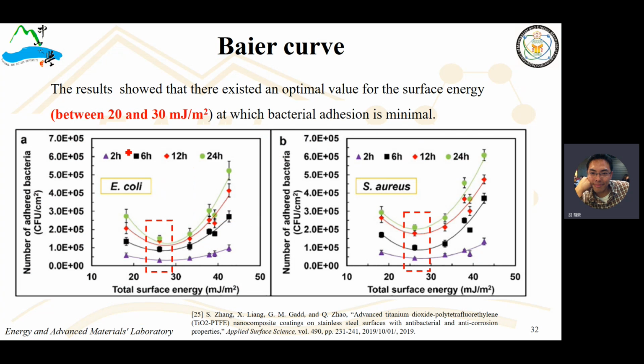And this reference shows the Baier curve. The Baier curve shows that when the surface energy is within a range between 20 to 30, it has the least accumulation of bacterial adhesion. This experiment used two types of bacteria. One is E. coli, and the other is S. aureus. These two types of bacteria were cultured on substrates with different surface free energy. And the Baier curve shows that a surface free energy between 20 to 30 has the optimum antibacterial effects.